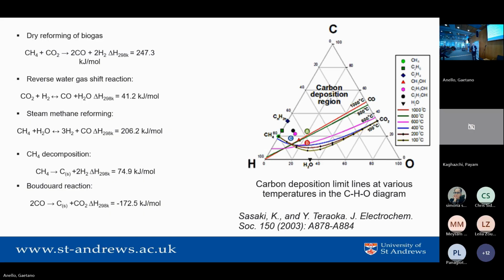So you have a range of reactions. Important parameters are the carbon, hydrogen, oxygen ratio. You want to avoid carbon formation, and at higher temperatures there's less coking. So you can avoid coking by going to higher temperatures or adding more oxygen through carbon dioxide or steam.